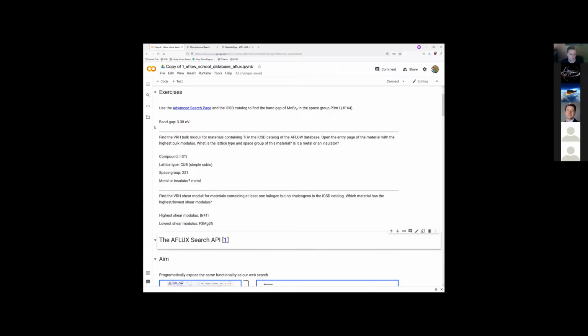We have some calculations. I think the calculations have a Hubbard U, which I think is in the standard parameters paper? I'm not 100% sure. Yes, in general the band gaps are corrected. So they are corrected with the plus U parameter, the Hubbard U. And that is part of the standard parameters paper. Yeah, there's a table with the list of U values, and for any given entry, you can also check the U value on that entry page.